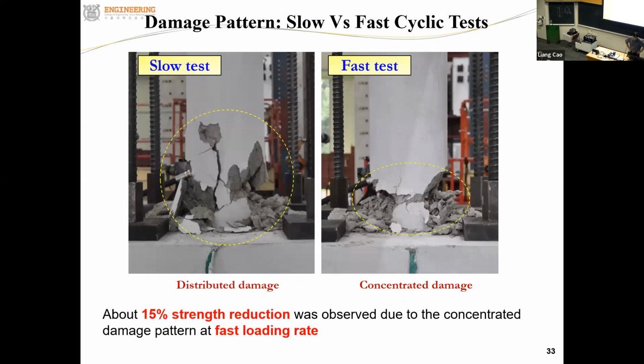All right, that shows the damage pattern after the slow test and the fast cyclic loading test. You can see the distributed damage pattern after the slow test, but with the real-time fast test, we see this concentrated damage pattern, which resulted in the reduced strength in this case. So it should be noted that with the slow test we have distributed damage, but with the fast loading test we have this concentrated damage, which can impact the strength as well as the ductility. We may even have earlier failure when you apply the real-time loading. So I believe it is very important to conduct real-time testing.